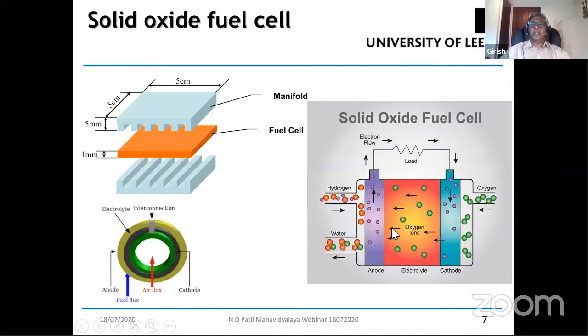The biggest drop occurs through the electrolyte, and therefore the thinner the electrolyte, the better it is. So if you have a thinner electrolyte, there'll be a lesser voltage drop. If you have a thicker electrolyte, you will have a larger voltage drop across the electrolyte. So that is one of the areas of research that is taking place. And for all these, to produce high surface area anodes and cathodes, or to produce a thinner electrolyte to sandwich between the two electrodes, there is a greater need for developing nanomaterials of all these components in a solid oxide fuel cell.